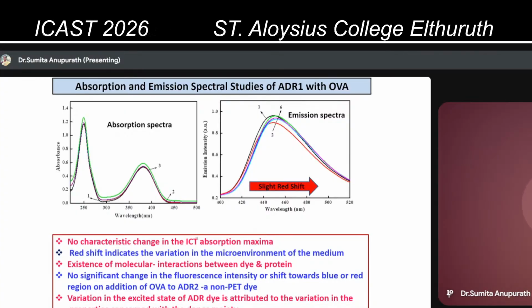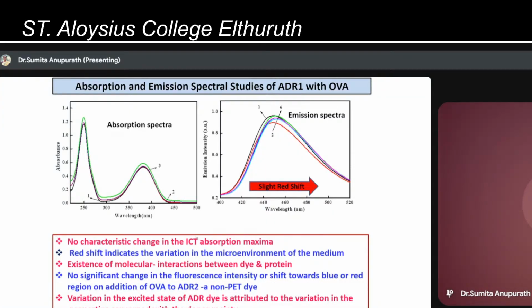Ovalbumin was treated with ADR1 and ADR2 dyes. The absorption spectrum of the ADR1 dye in the presence of ovalbumin again showed no change in the ICT absorption. That is again telling that the ground state is not affected. But in the emission spectrum, we could see a red shift, or a bathochromic shift, which shows that there is a formation of various microenvironments in the medium.